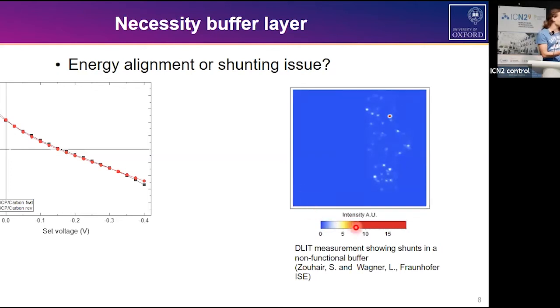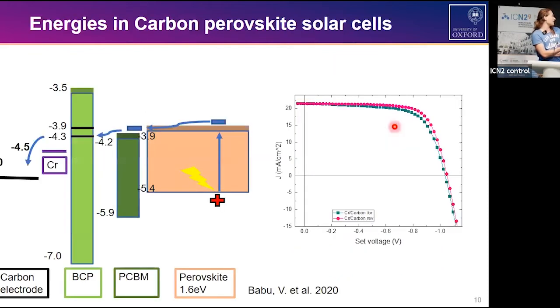So this is DLIT, a measurement on a 1 square centimeter carbon cell that was not working, and it shows local heat dissipation, which would be indicative of shunts in these devices. So from that point, I started looking at literature. There was not that much literature on PIN carbon, and I found something by Babu et al. from 2020. They introduced a chrome nano layer, just a few nanometers of chrome. I was not convinced that it would work.